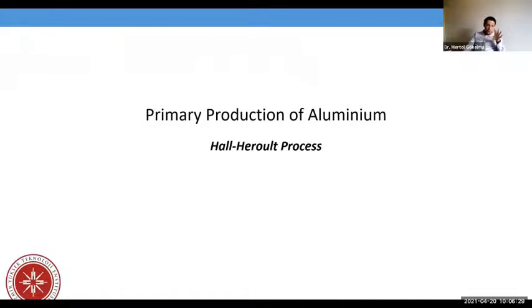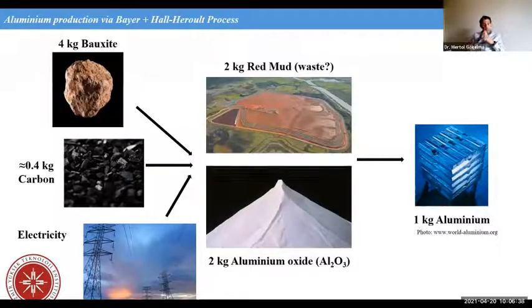I will start first, very shortly, with the Bayer process plus the Hall-Héroult process, which is very well known and used by many industries. The big picture is to produce 1 kilogram of aluminium. For every 1 kilogram, I use 4 kilograms of primary sources, our natural source, the bauxite, and approximately 0.4 kilogram of carbon and a lot of electricity, because it is produced by molten salt electrolysis. And for every 1 kilogram of aluminium, we produce 2 kilograms of red mud.